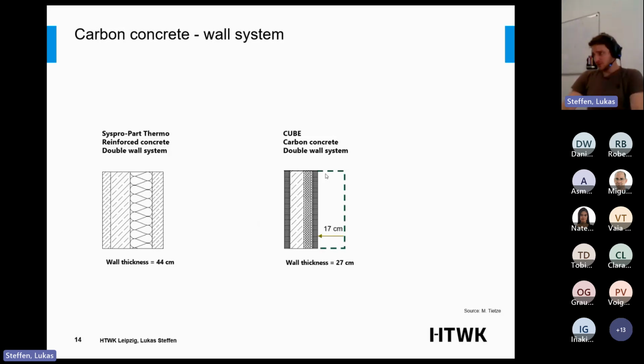If we use carbon concrete as a system in the Cube, we have up to 7% more marketable area, up to 35.6% less construction area, and our transport weights are reduced by up to 42.8%. So those are all factors that are good for the carbon concrete double system.